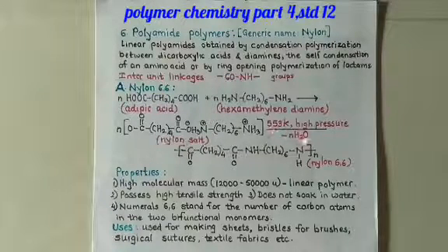These undergo condensation polymerization and form nylon salt in the first stage. So that is the structure of the nylon salt. Then nylon salt at very high temperature, near about 553 Kelvin, at high pressure eliminates water molecules and forms the polymer known as nylon 6,6. So this is the chain of nylon 6,6. In this, you can see there is a linkage of CONH. So NH continues with the CO groups and here CO continues with the NH group. So that is the amide polymer.